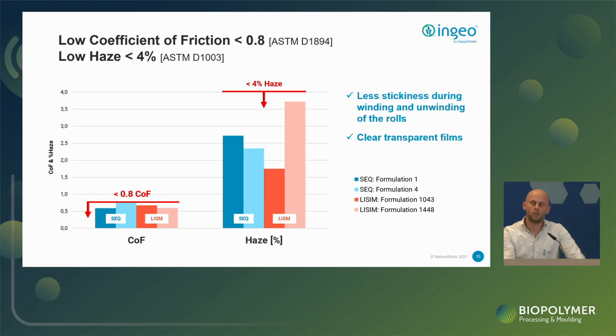But this is not the only important part here to talk about. Also, other properties are really essential for the post-processing especially. And that's on the one hand side the coefficient of friction. Here, the target was to be below 0.8, but this can still be adjusted by choosing the right master batch and the concentration, and then also the haze, which directly translates into the transparency of the film. Target is here to be below 4% haze, and you see all 4 formulations that we have developed are below that threshold. So that means those films are really highly transparent.